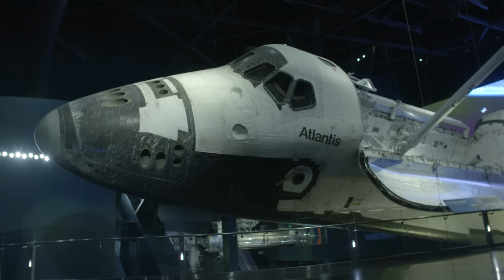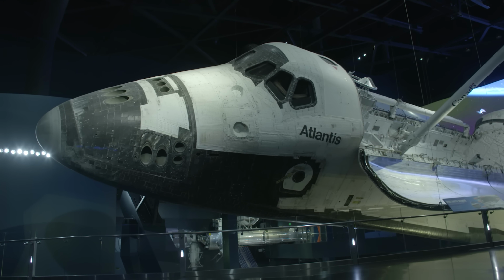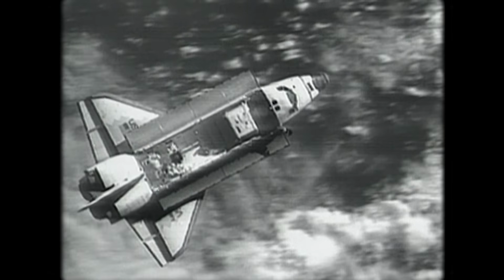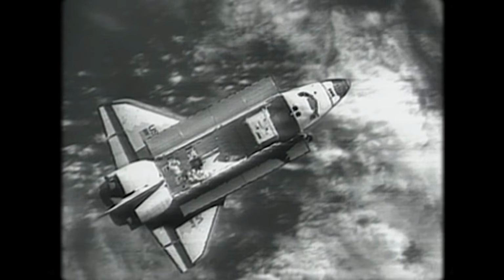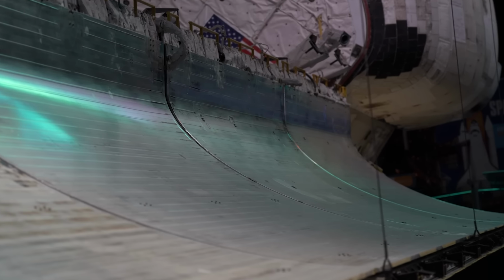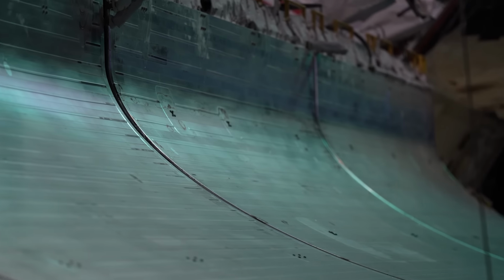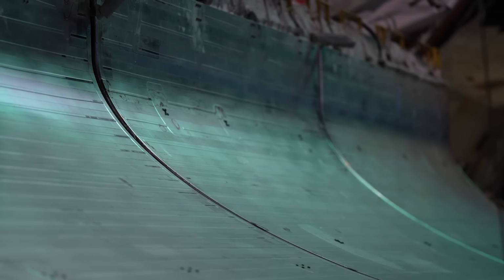So why isn't the entire space shuttle black like the SR-71? The space shuttle has one important difference with the SR-71. It exited Earth's atmosphere. Once outside the Earth's atmosphere, the intensity of solar radiation increases drastically. With the longest orbiter mission at 17 days, this heat had plenty of time to conduct through to the people inside. The orbiter did have huge radiator panels to reject heat to space, but to minimize their size, we want to reflect as much of that heat back into space, and for that reason, they are white. These tiles were coated with a similar glass coating, but with an aluminium oxide additive to provide the white coloring. The coatings also help to waterproof and strengthen these porous tiles.